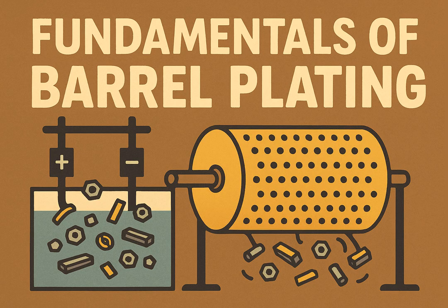For a DIY setup, they describe creating a plating solution, the electrolyte, using relatively common materials: distilled vinegar as the acid base, table salt to increase conductivity, and a source of pure nickel, like a piece of pure nickel metal. Vinegar and salt. Seriously. Yeah, for a simple acetate bath. They also use a DC power source, recommending a power supply over just batteries for stability and duration. And how do they get the nickel into the solution to start with? You need nickel ions, right?